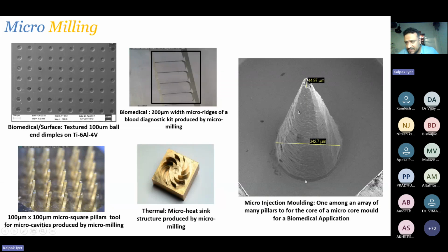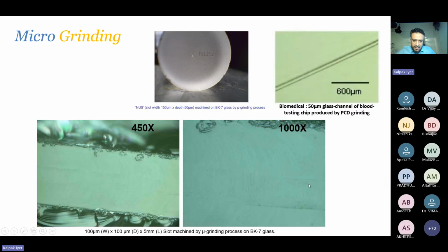This is a very challenging part that we did with IISc Bangalore, where this is SS316L, and we made these pillars. And you can see that the base of the pillar is about 350 microns, and the top had to be 40 microns. So very difficult to achieve this without breaking the pillar. This was done through milling, successfully at that. So micro grinding.